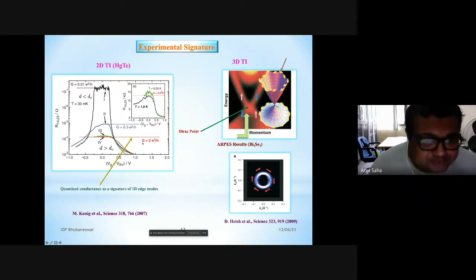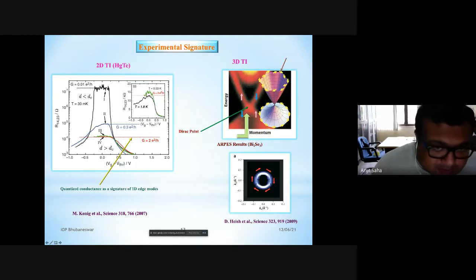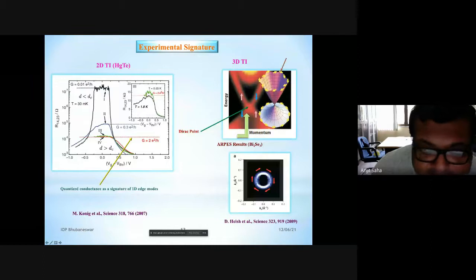And if you increase the temperature of the sample, due to thermal fluctuations the response is quite robust. There are small thermal fluctuations here, but it remains quite close to the quantized value. So these helical edge modes actually correspond to a quantized conductance of 2 e squared over h, which they showed in the experiment, and which clearly explains that from the experimental point of view, one can distinguish between the trivial and the topological phase in mercury telluride.